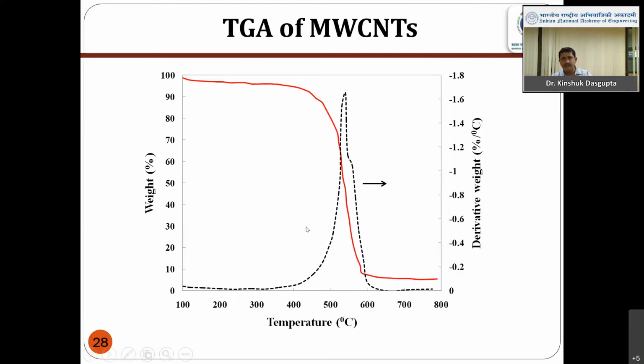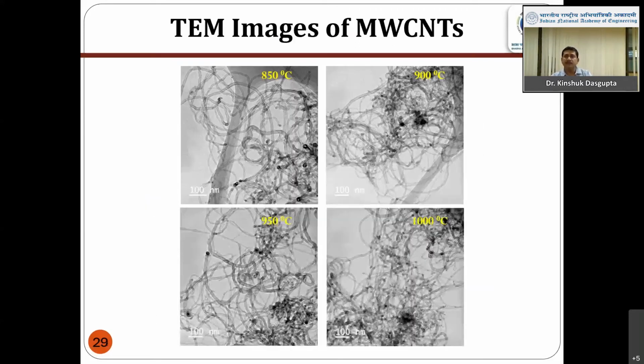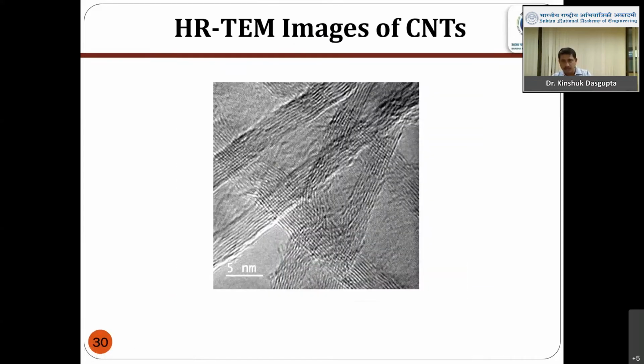If it is amorphous carbon, then being a high energy phase, it starts oxidizing earlier. Secondly, if we take the derivative of them, we get a different rate of reaction. So from there we can come to know how many phases are present. Then we take it to transmission electron microscopy, which should show a tubular kind of structure. And if we go for high resolution electron microscopy, we can even count the number of walls. This is the inner diameter, this is the outer diameter, and around 8 to 13 walls are present in the nanotube that I can show here.